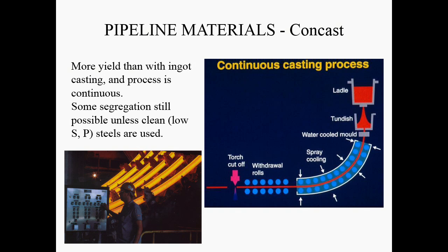So this process is widely used. Because of this bending, you can't have a material which is susceptible to cracking, so it has to have high enough toughness. So this process couldn't have been developed until the killed steels came along that were higher toughness. But nowadays, almost all steels that are used in a plate or bar stock product form are made by this process. Special alloy steels still have to be cast in a batch form because the total volume of production doesn't justify this sort of process.